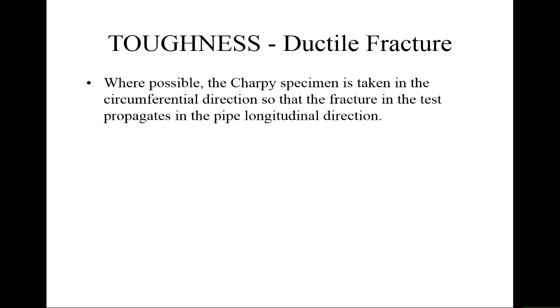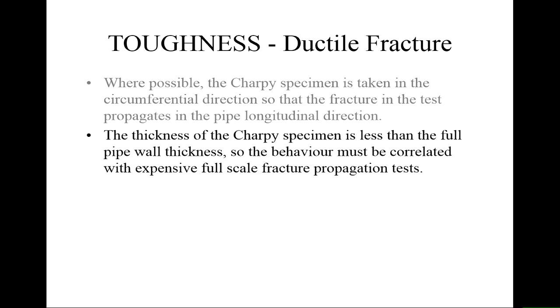Again, as I said, where possible, you take the Charpy specimen in a circumferential direction so that the notch and the fracture propagate in the longitudinal direction for the pipe, because that's what happens in real life. You can't always do that. If the pipe is too thin walled, then you may not be able to. The thickness of that sample is less than the full pipe wall thickness. So if there are problems with defects and non-uniform composition across the wall thickness of your pipe, which there often are, the surfaces are different from the bulk, then you'll have to do some experiments to correlate a full-scale pipe test with a Charpy test.